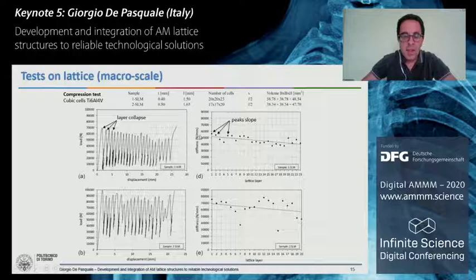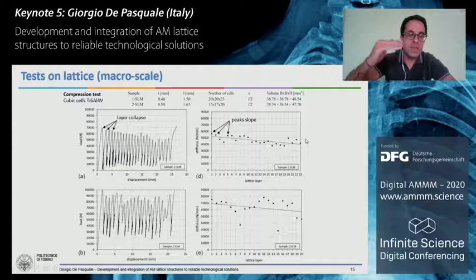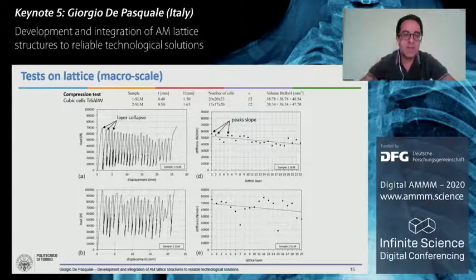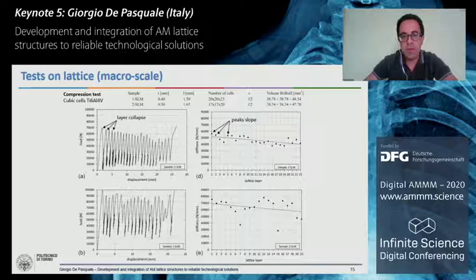In a diagram where we plot the stiffness of the single layer depending on the number of collapsed layers, we also observed a trend like this, testifying to a progressive lowering of stiffness during the collapse of each single layer of a lattice structure.